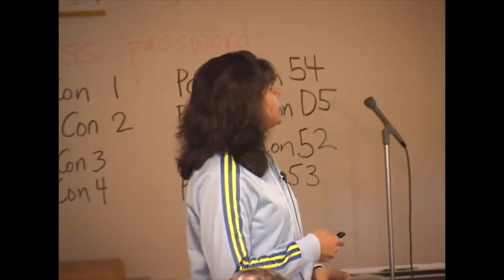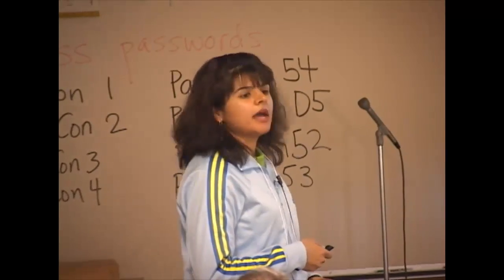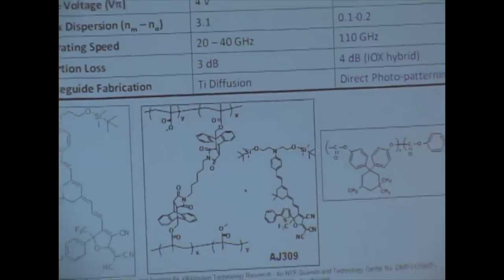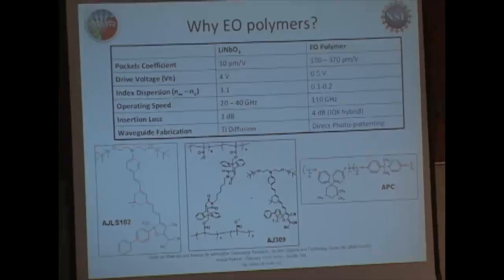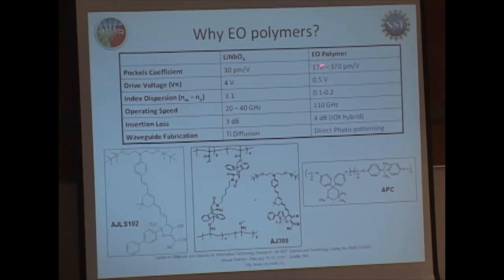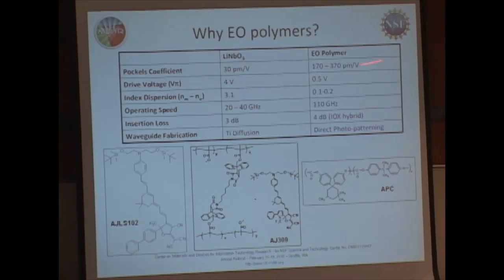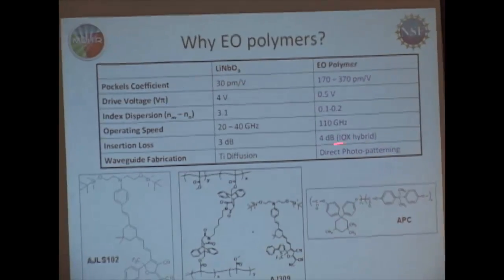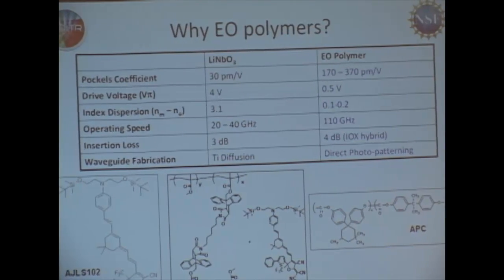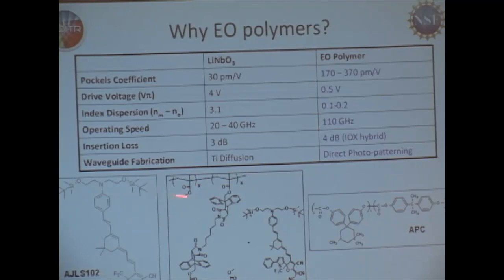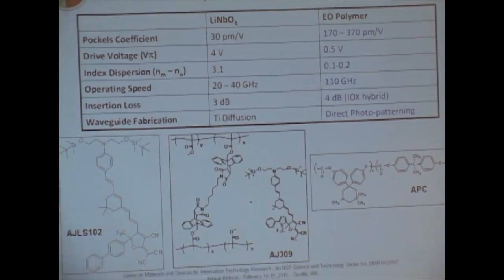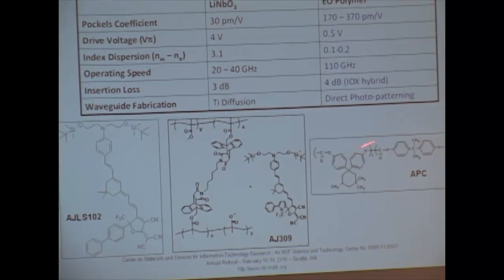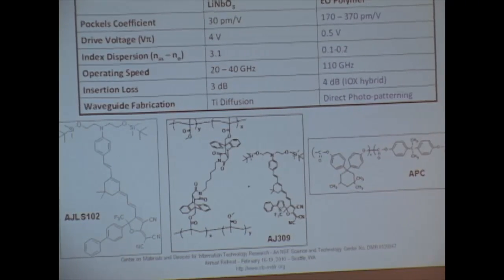So why are we using EO polymers? Basically, we want to try and replace the lithium niobate modulators with the EO polymers. And in this case, the EO polymers are much better because their Pockels coefficient can be modified based on the side chains that you modify on the chromophore. And we can go down to 0.5 volts in the drive voltage. And we've also gone down to 4 dB loss with ion exchange waveguides. And then these are some of the polymers that we've used courtesy of Alex Jen. And APC is our host polymer.